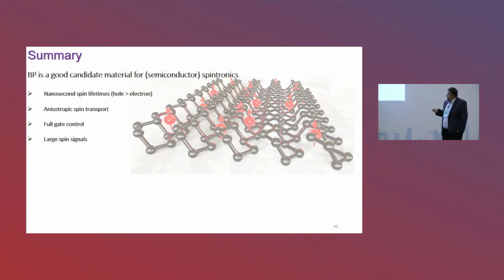And by developing a very effective encapsulation process, we can make this material air stable, and we can observe spin lifetimes exceeding nanoseconds. And because of this puckered crystal structure, its electronic properties, the Raman properties, the vibrations, everything is anisotropic. We do also see that the spin transport properties are anisotropic in this material. So basically, by combining this material with some other 2D materials that I cannot go into detail, you can control the spin propagation within this material by just making some van der Waals structures, also using other materials with high spin-orbit coupling. And we have full gate control, meaning that we can turn on and off effectively by using the gate voltages.